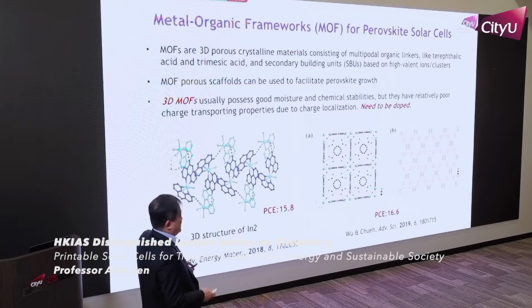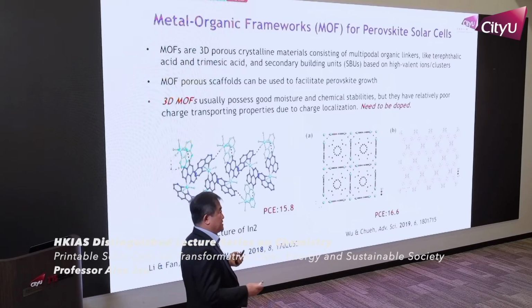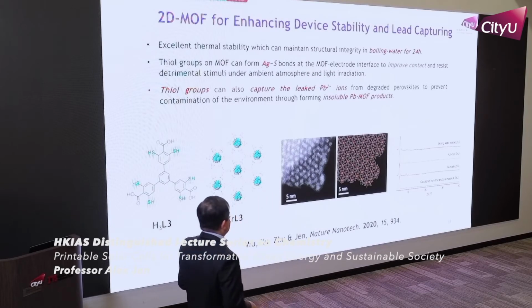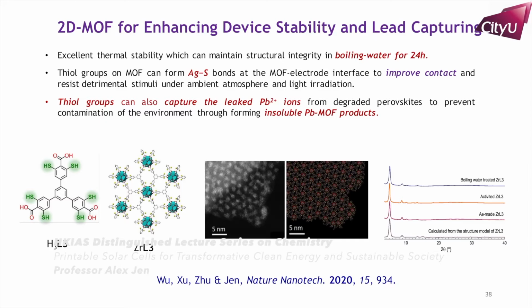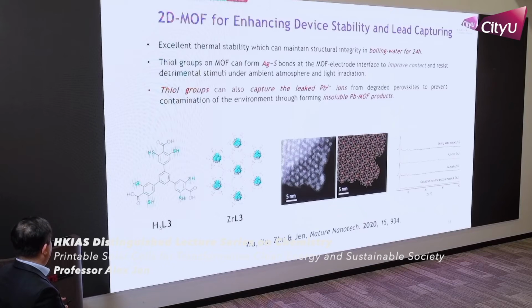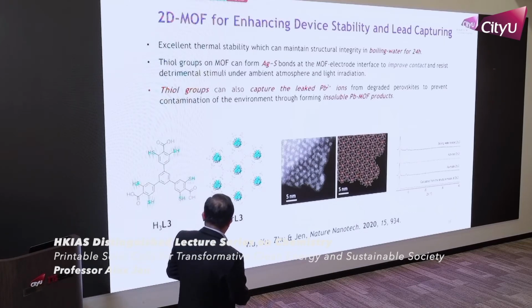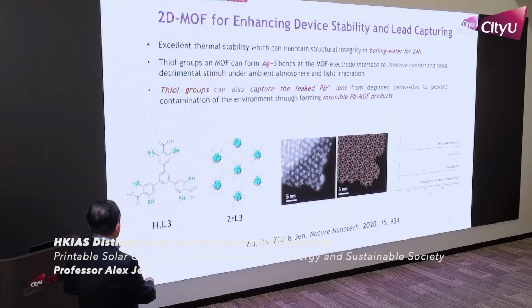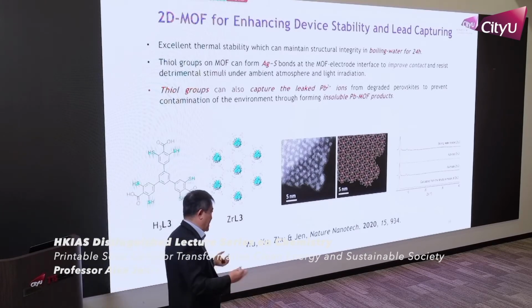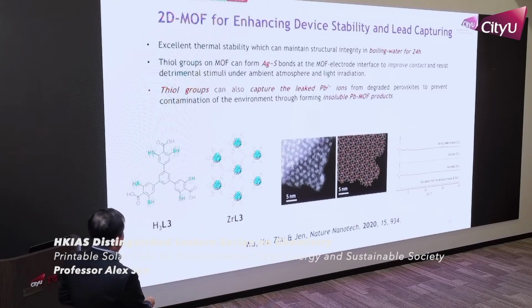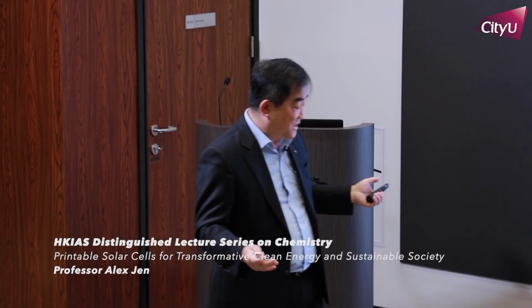So it's very limited if you want to use that for solar cell applications. So Zhentao came up with a design. They take some organic conjugated units and design them with many SH groups attached to this linker. When you react the carboxylic acid with zirconium, they form a very nice 2D network, because the SH provides some steric hindrance from making the 3D. And one thing very nice is this SH has a lot of functionality.